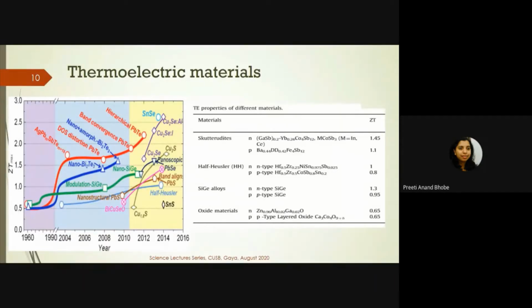The early 60s used bismuth telluride and bismuth selenide kinds of semiconductors. Their ZT was very low, 0.5 or so. The improvement started in the early 90s, when people started making nanomaterials and combinations of different thermoelectric materials in the basic bismuth telluride systems, and they improved the ZT. But again, for a long time, till 2012, 13, it reached a plateau. There was no further rise. Then another new material started coming up in the early 2010, 2012 era. And not only bismuth telluride, people started looking for different combinations.